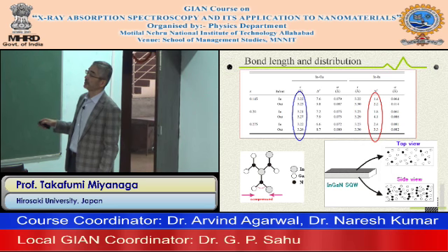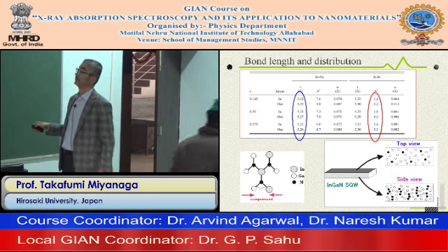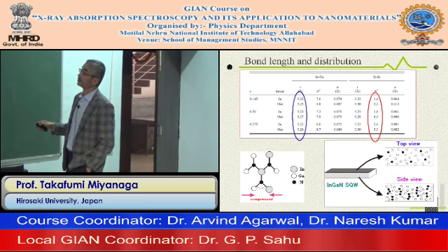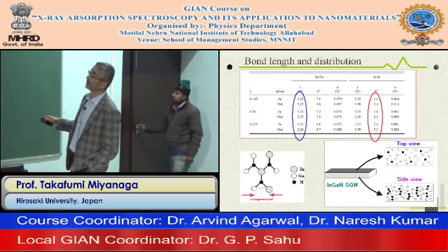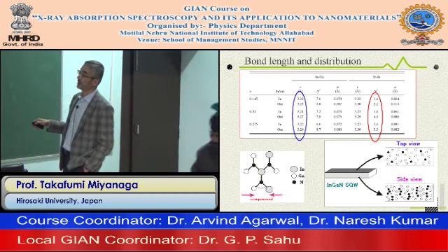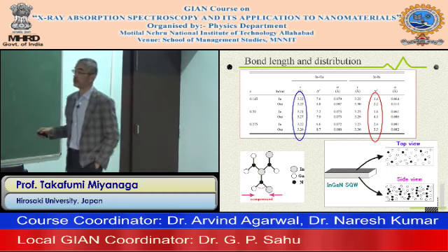In plane it is 3.22 angstrom, and out of plane is longer. Indium-indium is also longer out of plane than in plane.